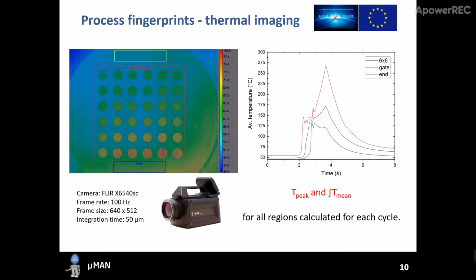This is an example of how we extract process fingerprints from thermal imaging. This is a thermal image taken from the ultrasonic micromolding cavity, and as you can see, we have different regions of interest. For example, this is a square region of interest that has been put on this 6x6 microneedle array. We are also interested in temperature distributions near the gate and towards the end of the cavity. We also extract these temperatures as temperature curves, which you can see on the right hand side.